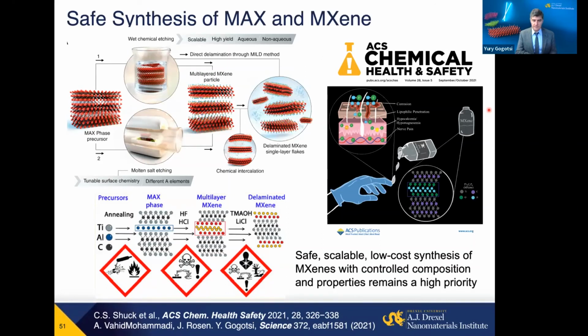You remember I mentioned the possibility of grafting organic molecules, for example, reacting amino groups or electrostatically attracting amines to negatively charged MXene surfaces. They're actually more forgiving than graphene to a large number of layers because of the strong interaction of MXene, so you don't need to delaminate them completely. And of course, having Young's moduli in the hundreds of gigapascals and mechanical strengths of single flakes in the range of 10, 20, 30 GPa, they clearly can provide very efficient reinforcement for polymers, simultaneously potentially increasing conductivity, dielectric properties, and a number of other characteristics. So definitely exploring MXene-polymer composite systems in films and fibers as bulk reinforcement or modifier of properties is a very, very efficient way of bringing them into applications.